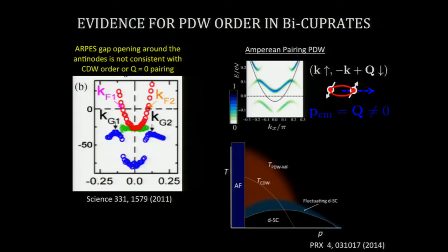Observation of angle-resolved photoemission shows that when the gap opens up, for example for the density wave state in that dome, ARPES can make that measurement: the gap doesn't open at the same k as where the Fermi surface intersected the Fermi level. That k seems to shift. And that's odd. A density wave shouldn't do that.